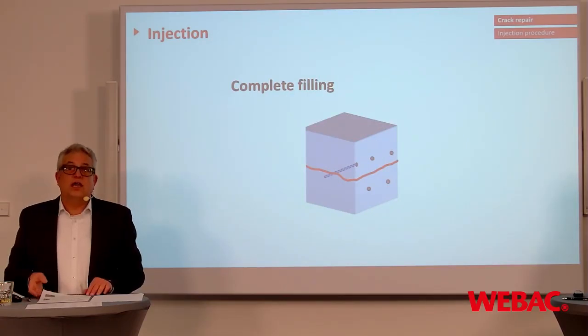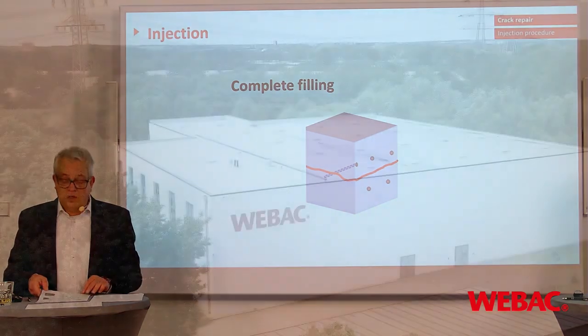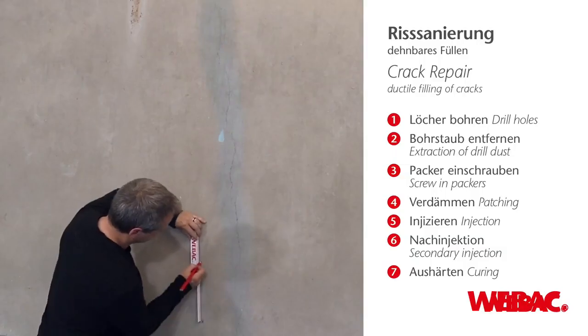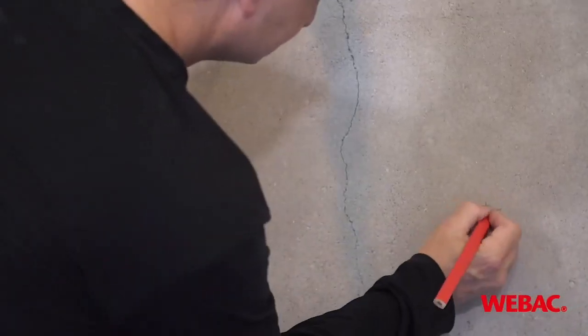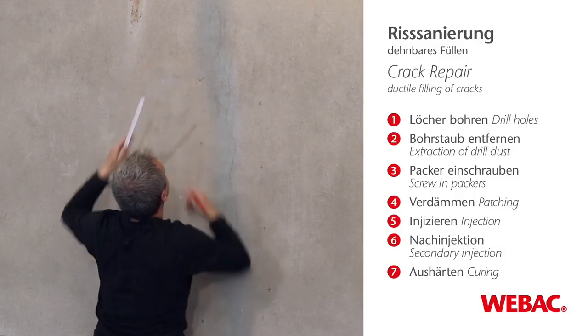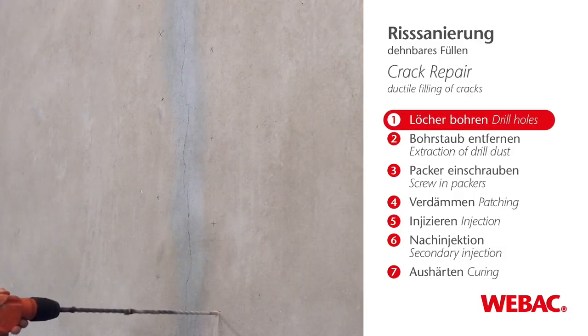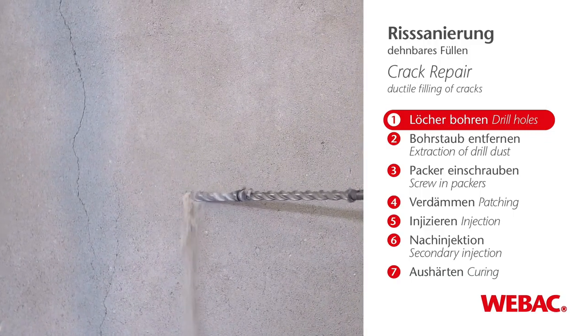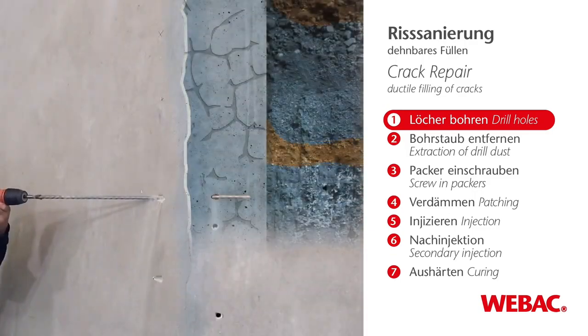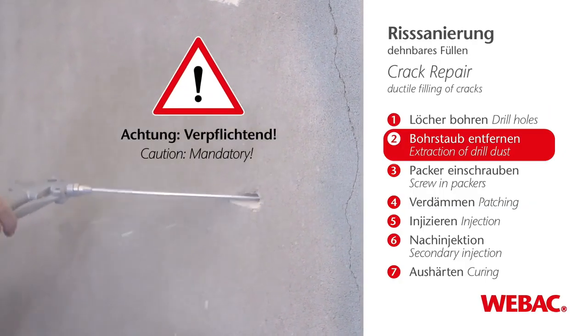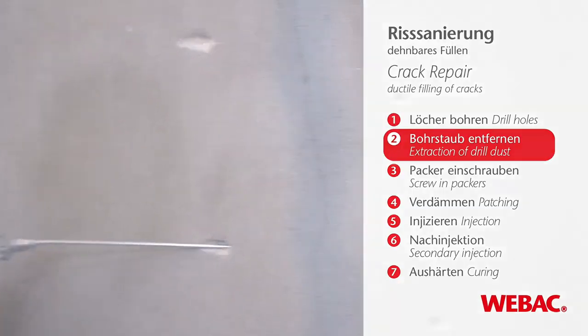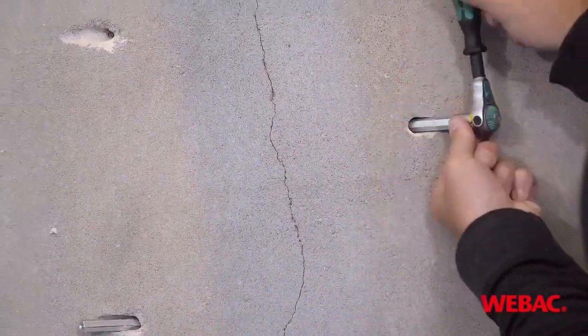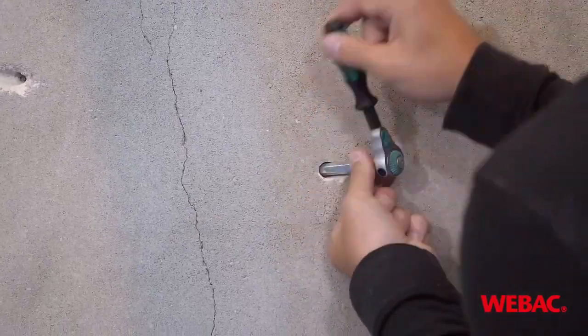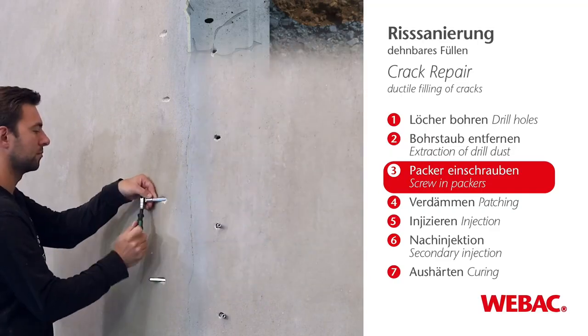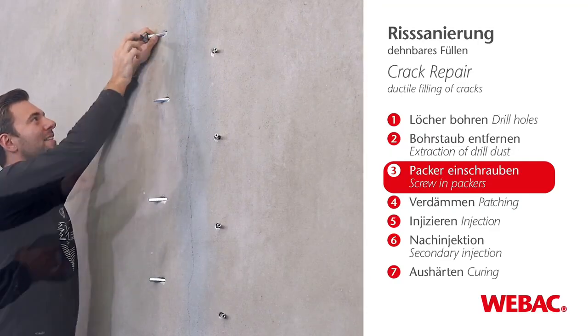So how this works now, we have prepared a small video and let's take a look at this. So here we see a wet crack, I would say. Drops are coming out of the crack. First of all, you mark your drill holes in the distance we discussed. Then you are drilling, you can see it here very good in this angle, to hit the middle of the construction. Very important to remove the drill dust, because that's quite easy to understand. If you are pressing the drill dust with the injection material into the crack, then you block it and the injection process will not be so easy.